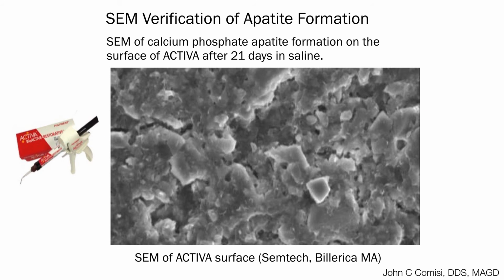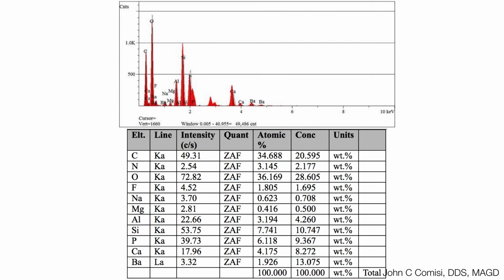We cannot stress enough how important the formation of apatite is for the best long-term outcomes for all restorations. And this SEM shows the apatite formation with Activa, 21 days stored in saline. In fact, the company has SEMs that show how it penetrates through all adhesives that are currently available. So this ability to occlude the gaps and seal the gingival margin against microleakage is an important goal, in my opinion, as we've been talking about, for long-term success. And here is the EDAX of the apatite that was formed, for those of you who understand this a lot better than I do. So you can use that to compare and contrast.